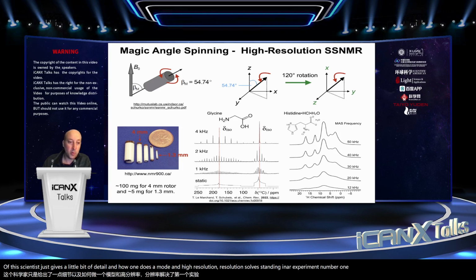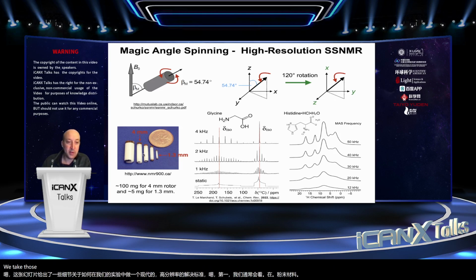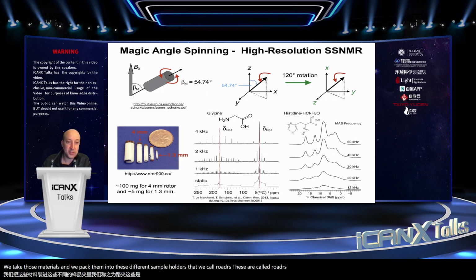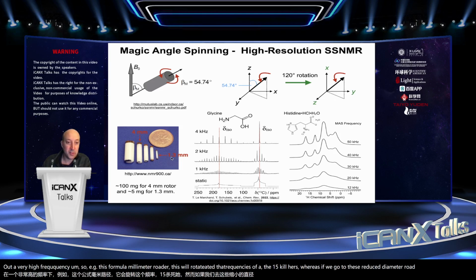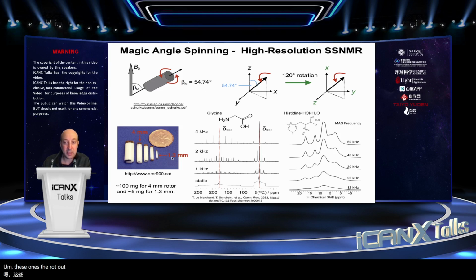Number one, we're usually going to be looking at powdered materials. We take those materials and we pack them into these different sample holders that we call rotors. These are called rotors because they're going to be rotating at a very high frequency. So for example, this 4mm rotor will rotate at frequencies of up to 15 kilohertz. Whereas if we go to these reduced diameter rotors, these ones will rotate at around 60 kilohertz if we push the spinning frequency.